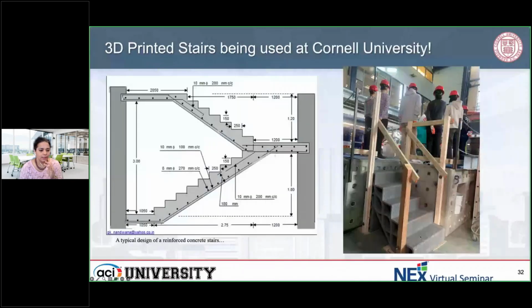So like I said, we printed this geometry and then we tilted it to the side, and we are using these as steps. This is an example of how a typical reinforced concrete stairs could look. Of course, the span here is small, but what I want to show you is how this was designed such that because concrete is really good in compression, we designed arches such that the forces are transferred onto the arch in a compressive manner. And because the layer-to-layer bonding is so good, we're able to use them as stairs. We also put a huge point load to make sure that this was strong enough to take like 1,000 pounds in a small square foot of area. So, like I said, because concrete is good under compression, we've also printed these arches.